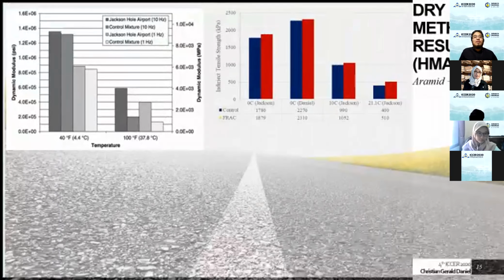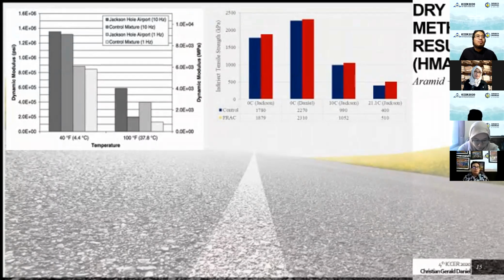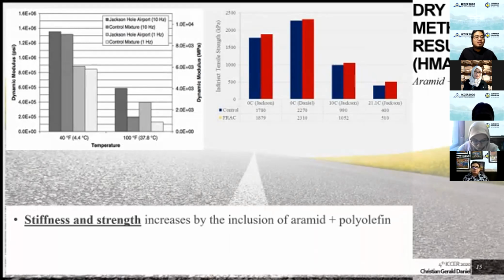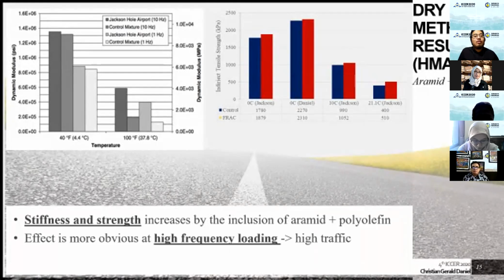What about the dry method now? I haven't mentioned aramid yet because it has a high melting temperature, which means that it cannot just melt inside the bitumen using the wet method. So it acts more as a mechanical reinforcement using the dry method. And by combining aramid and polyolefin, we could have something like this. Stiffness and strength basically increase. And the effect is more obvious at high frequency loading, indicating a better performance maybe at high traffic. And also it is more apparent at high temperature, where the bitumen becomes more viscous so that the fiber could react better than in the previous stage.